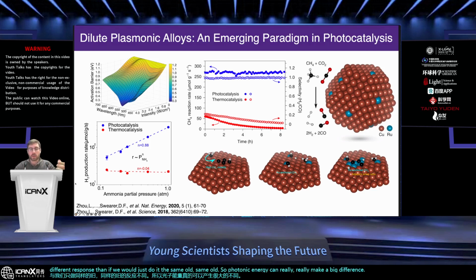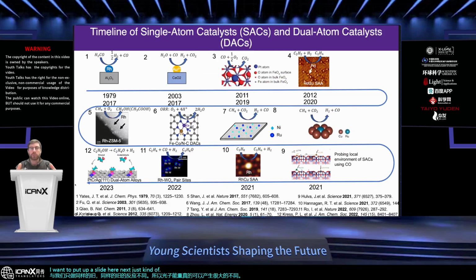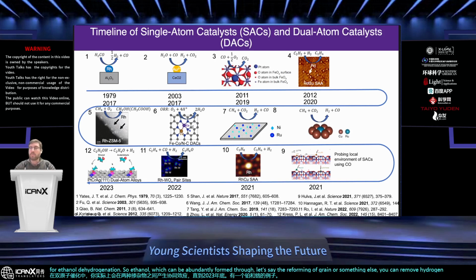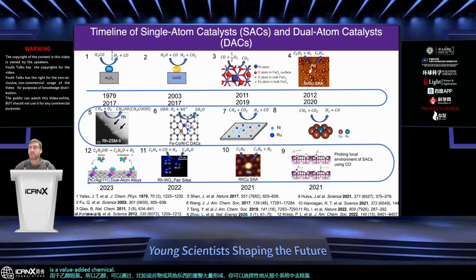I want to put up a slide here next, just kind of acknowledging that there's a long history of single atom catalysis, and now there's an emerging area of dual atom catalysis where you actually get synergistic effects between two dopants all the way down here at the end in 2023. There's an example of platinum and copper for ethanol dehydrogenation. So ethanol, which can be abundantly formed through, let's say, the reforming of grain or something else, you can remove hydrogen from that system selectively, make acetaldehyde, which is, again, a value-added chemical precursor, and generate hydrogen all at the same time.